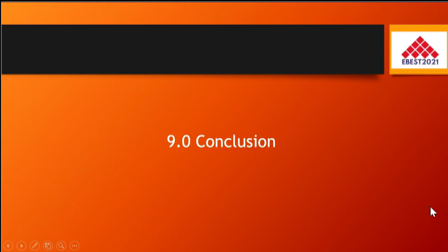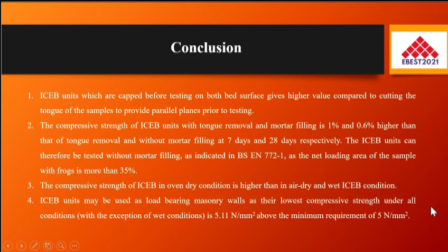As for the conclusion, this study shows that ICEB units which are capped before testing on both bed surfaces give higher values compared to cutting the tongue of the samples to provide parallel planes prior to testing. Second, the compressive strength of ICEB units with tongue removal and mortar filling is 1% and 0.6% higher than that of tongue removal and without mortar filling at 7 days and 28 days respectively.